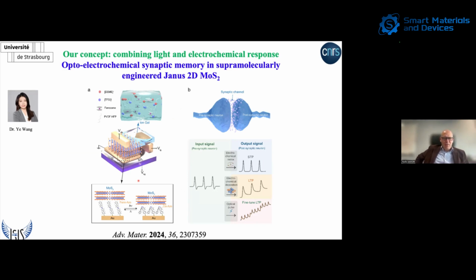And the idea was, again, the Janus type of approach, interfacing the two-dimensional materials in an asymmetric fashion with two different environments. The two-dimensional material that was chosen was molybdenum disulfide. We had a bottom gold electrode that was covered by a chemisorbed layer of azobenzene, which can undergo isomerization from the more extended to the more compact form, so from trans to cis. And the top of the molybdenum disulfide was interfaced with an ionic gel, in which we dispersed ferrocene molecules. Ferrocene, of course, is subject to electrochemical stimuli.